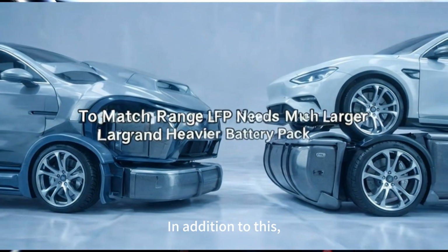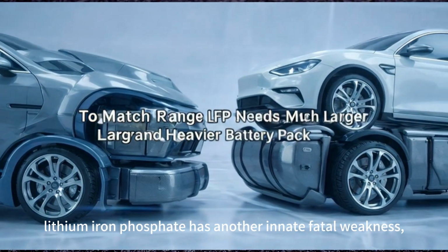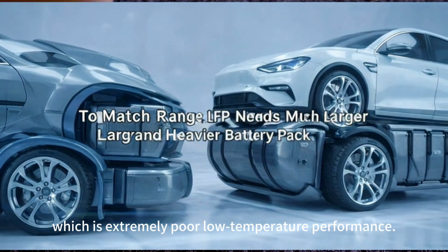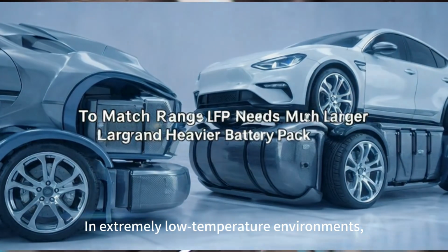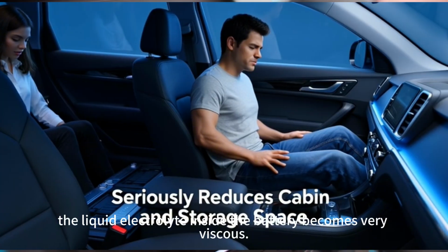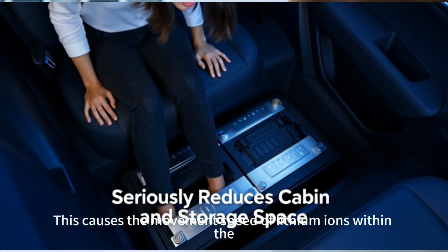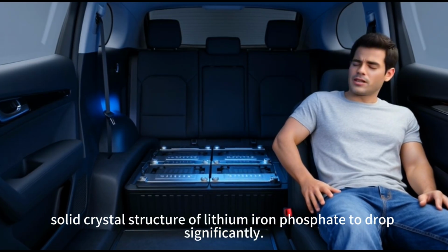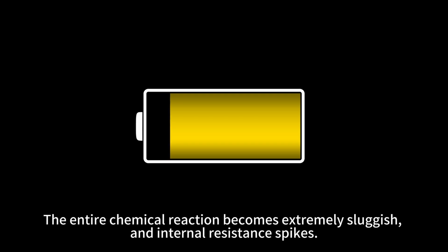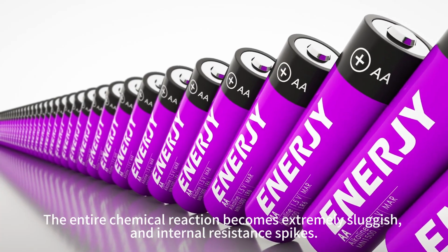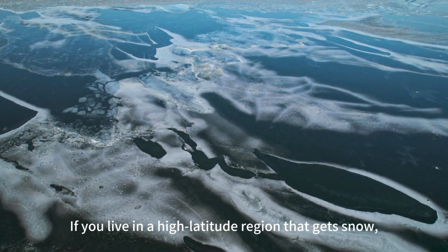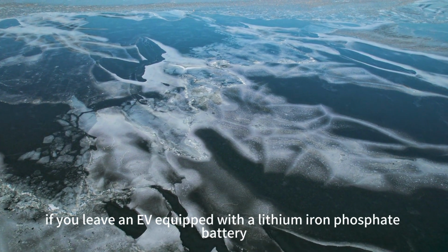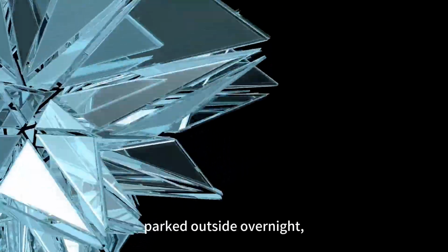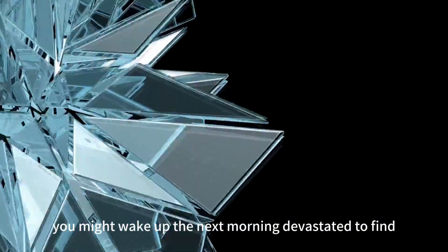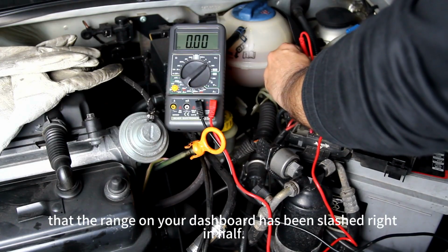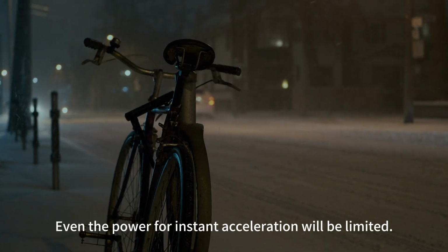In addition to this, lithium iron phosphate has another innate fatal weakness, which is extremely poor low-temperature performance. In extremely low-temperature environments, the liquid electrolyte inside the battery becomes very viscous. This causes the movement speed of lithium ions within the solid crystal structure of lithium iron phosphate to drop significantly. The entire chemical reaction becomes extremely sluggish, and internal resistance spikes. If you live in a high-latitude region that gets snow, in the dead of winter at -10 degrees, if you leave an EV equipped with a lithium iron phosphate battery parked outside overnight, you might wake up the next morning devastated to find that the range on your dashboard has been slashed right in half. Even the power for instant acceleration will be limited.